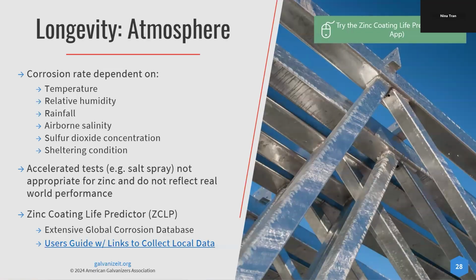All right, longevity in the atmosphere. We get this question a lot. How does galvanized steel last so long in pretty much any environment? And we like to point out that galvanized steel is a 150-year-old process. So it's been around for a while, it continues to get better, but we have tons of real-world data to go off of. A lot of times people will rely on salt spray testing as reliable data, and with galvanized steel, it does not accurately mimic real-world conditions because it doesn't allow the zinc patina to develop. And the zinc patina is critical in the longevity of the hot dip galvanized steel.